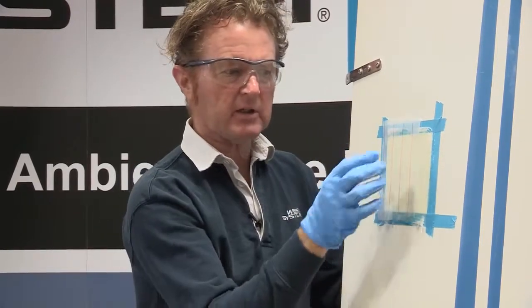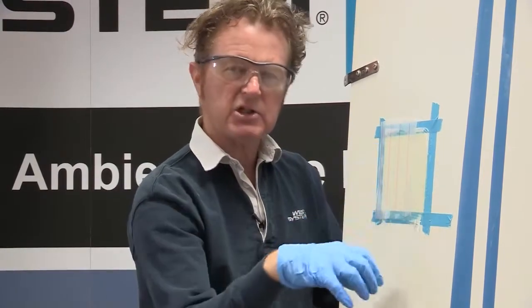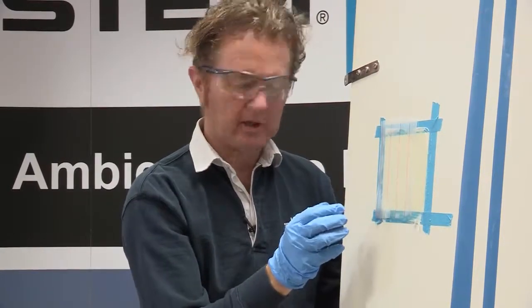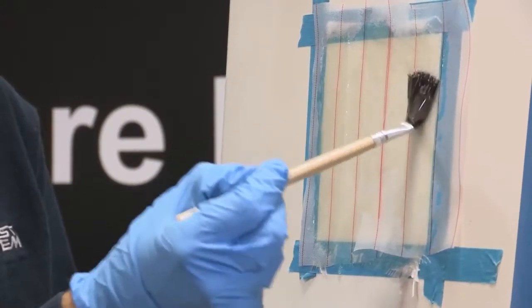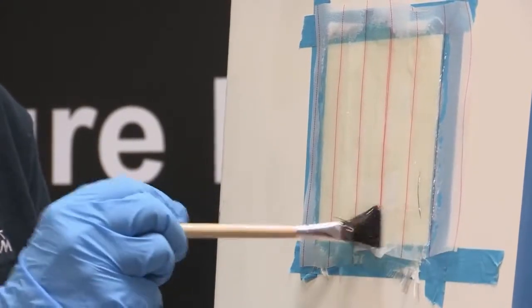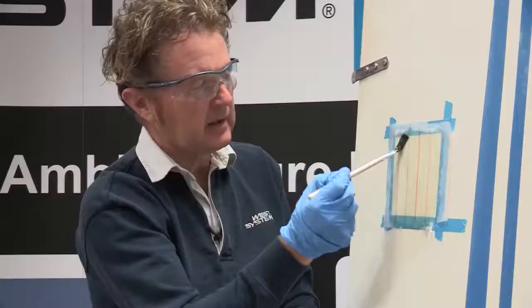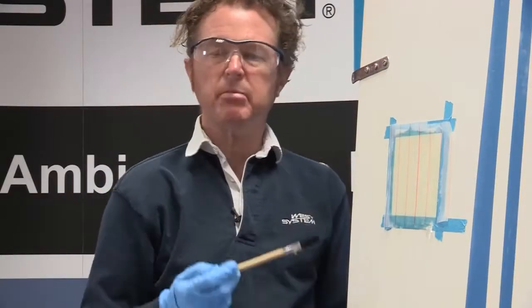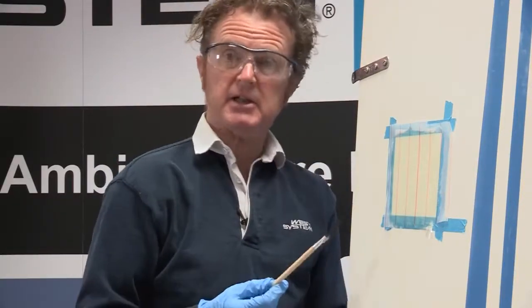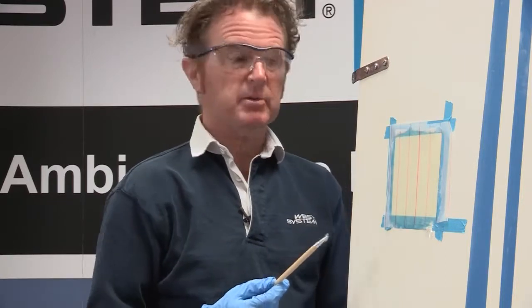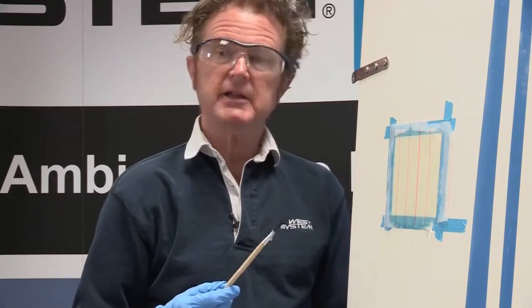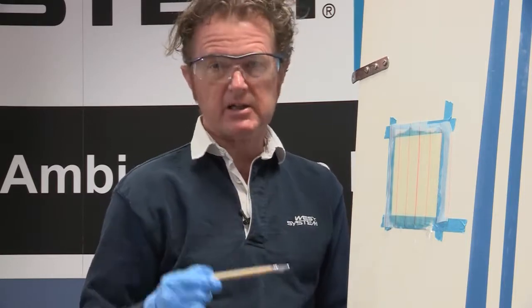And very importantly, we want this face to stick against the inside of our hull when we conduct our letterbox repair. And you can overlap this. There's no issues with overlapping it. And I'll just stipple this down. And that's my backing patch complete. I now have to leave this to cure overnight before I can release this away and then use it as my backing patch in the letterbox repair.